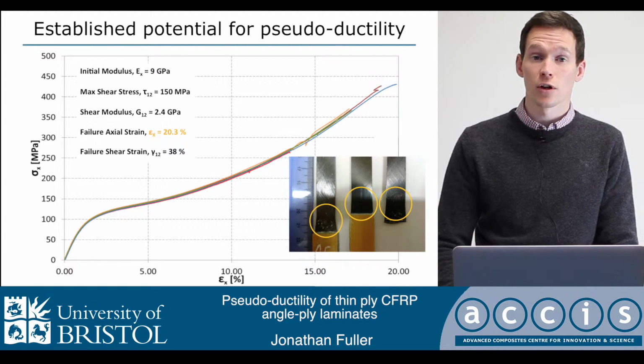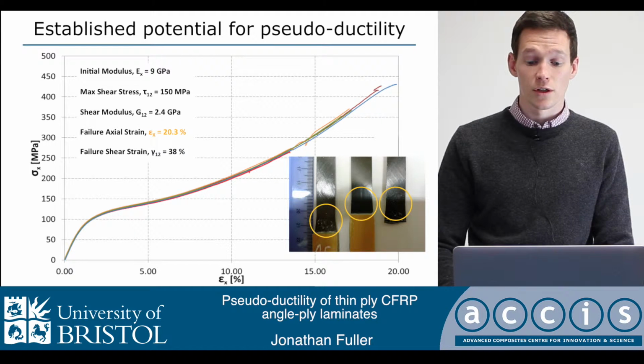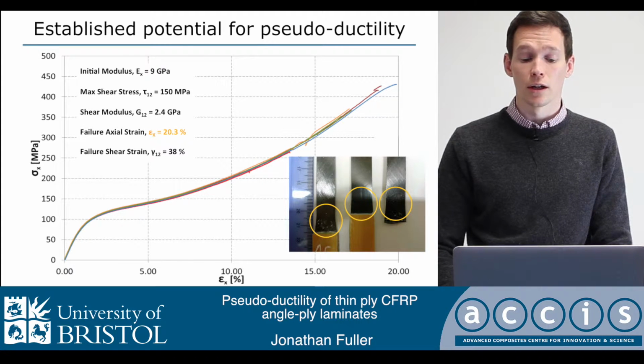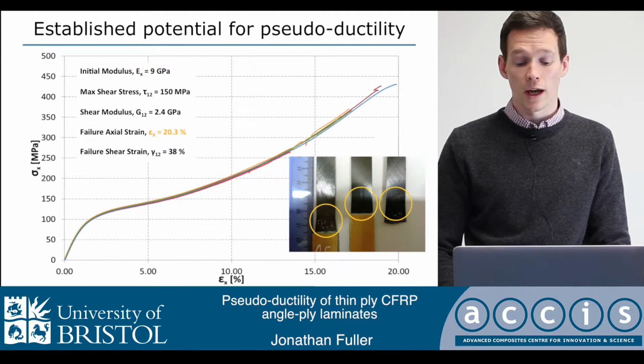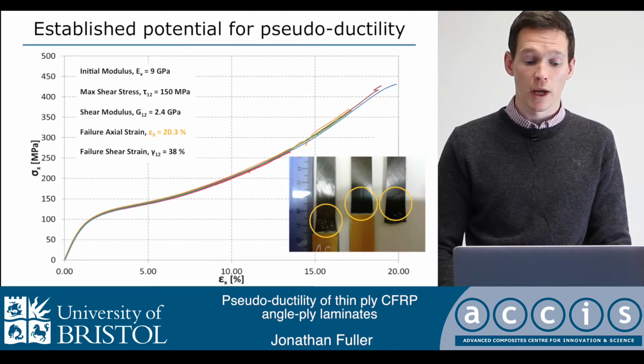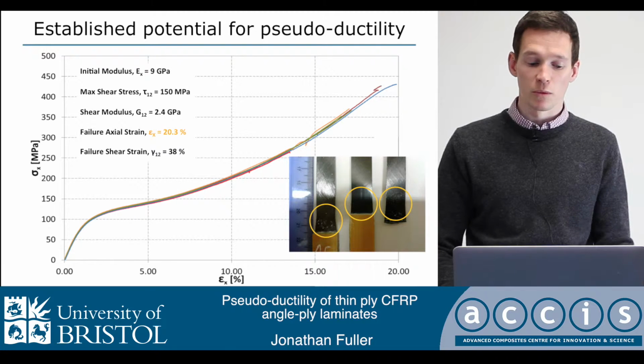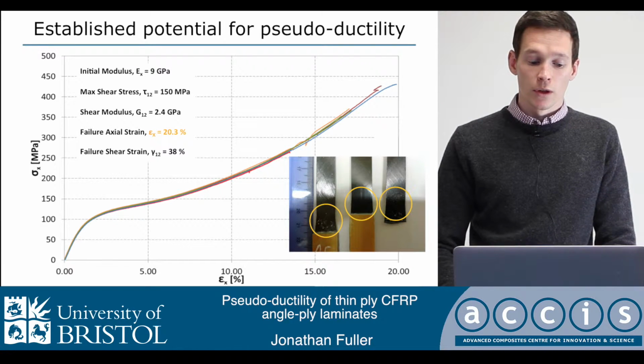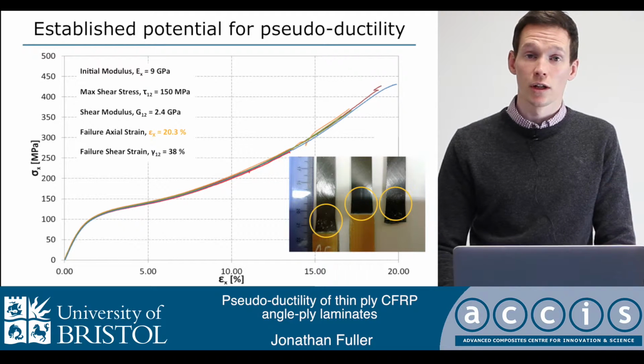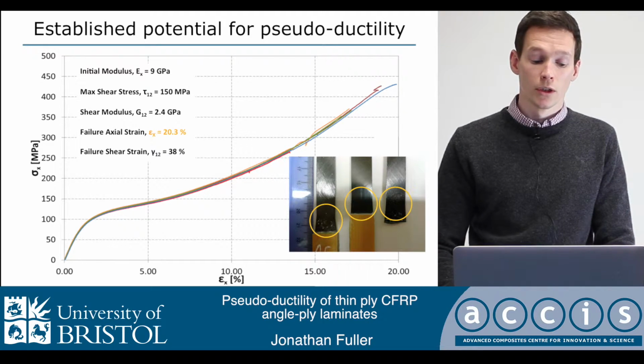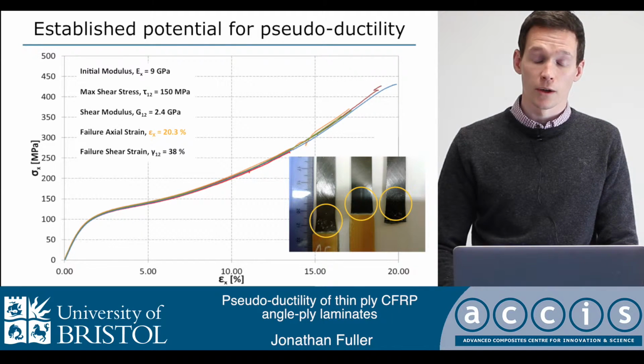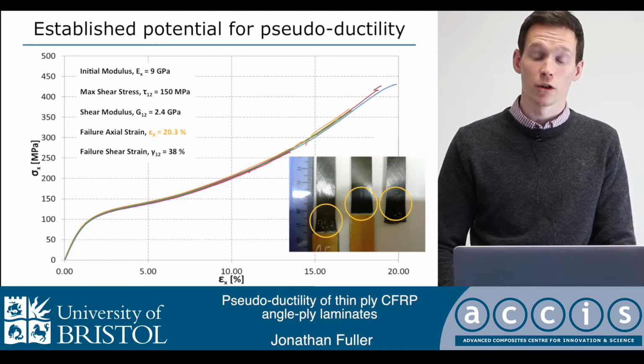So initial results characterizing the material showed that this is a plus or minus 45 laminate, and here we've got a highly nonlinear response with strains in excess of 20% to failure. Also, the inset picture shows that there's large necking at the end tab region, which is a metal-like behavior, showing something similar to what you might get in a ductile material. The thing to note, though, is that the initial modulus is only 9 gigapascals, which is low. So the idea we wanted to try was, can we create a similar behavior but increase the initial modulus?